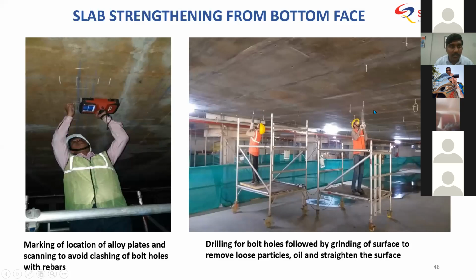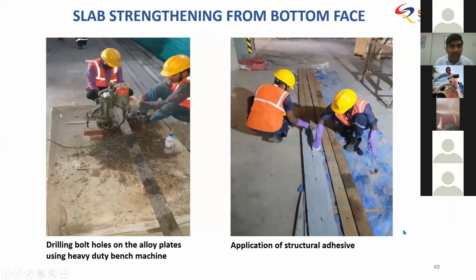Drilling, because we need to anchor the strength-providing high strength alloy plates onto the bottom of the slab using chemical anchors, which are drilled into the structure. At the time of drilling, we should not hit the existing rebars, which is why this initial scanning was done. Now these plates that you see on screen are the high strength Fe 450 grade alloy plates.